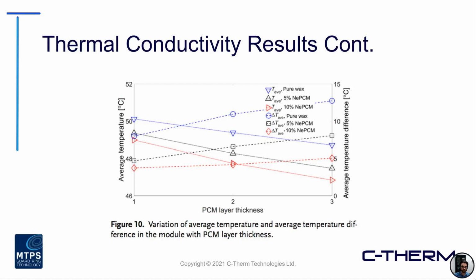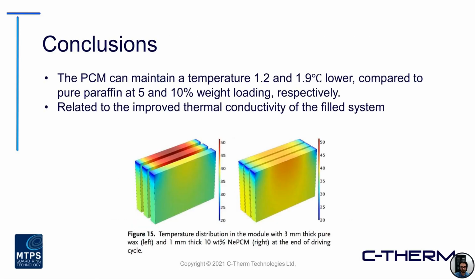But really here, they were able to show that the average temperature of the system was much lower when you added in that additive to the base PCM. Also, looking at it in the sense of increasing PCM layer thickness, you note that the average temperature does show a steady decrease with PCM layering related to the increased additive that is present.